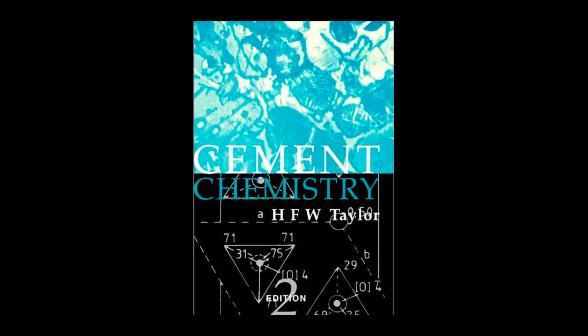And then there are the alkalis, sodium and potassium, which are notorious for attacking certain types of stone, right? Yes, the alkali content, Na2O and K2O, is often restricted to something like 0.6% equivalent Na2O. This control is aimed squarely at mitigating something called alkali-silica reaction, or ASR.